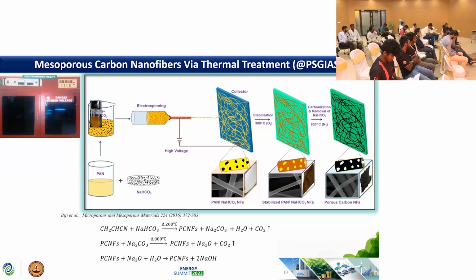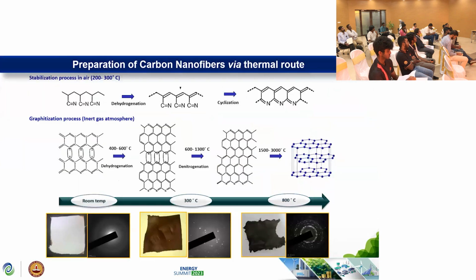Further, we stabilized these polymer nanofibers at 300 degrees Celsius under an oxygen environment, followed by carbonization. To remove the sodium bicarbonate, we carried out carbonization at 800 degrees Celsius in a nitrogen atmosphere. During this process, thermal decomposition of sodium bicarbonate was observed, and we then did water washing so that the entire sodium hydroxide that had formed was removed, leaving mesopores on the surface of the carbon nanofibers. So what is going on during the stabilization process in air? Dehydrogenation and cyclization of the PAN fibers happen, followed by graphitization in an inert atmosphere. During this, dehydrogenation followed by denitrogenation happens, and graphitic domains are formed with some nitrogen sites.